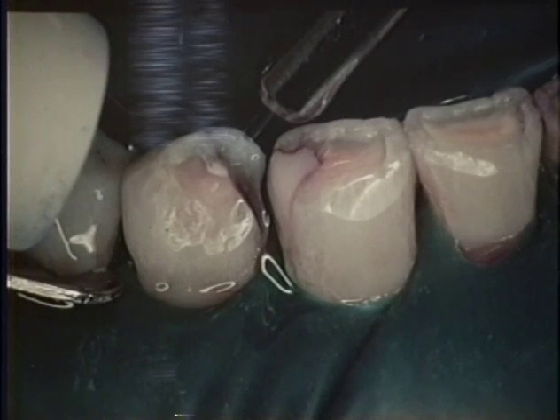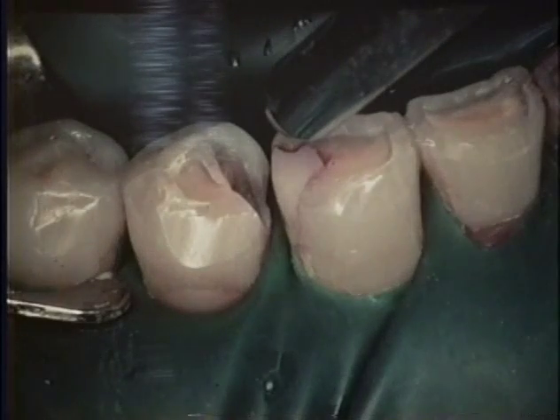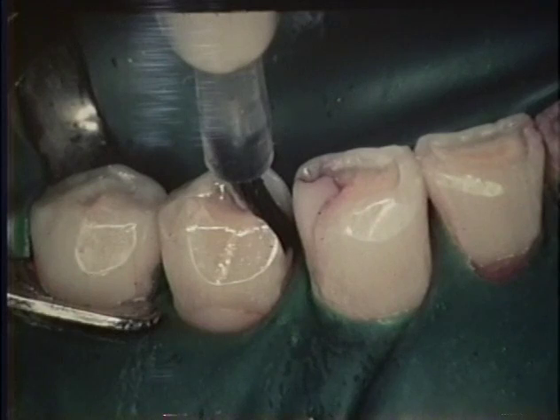You can remove collagen, for example, with sodium hypochlorite. 10% hypochlorite will take the collagen off and allow a better bond for a lot of materials. In this particular case, we're going to kind of ignore the collagen, hope it isn't around, although it is. So we're going to dry that off there. Okay, we're going to dry off the ethanol. Okay, drying off the acid.